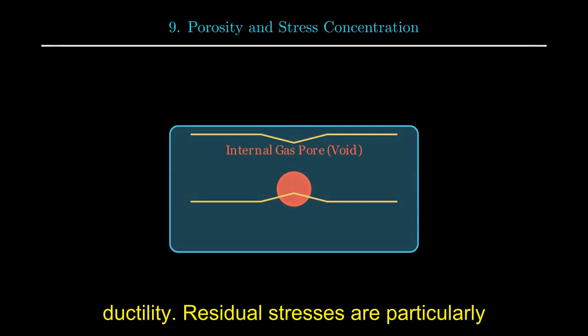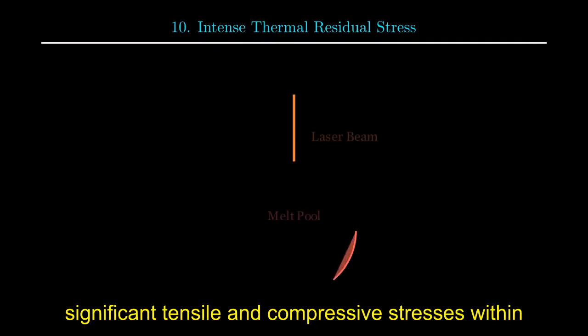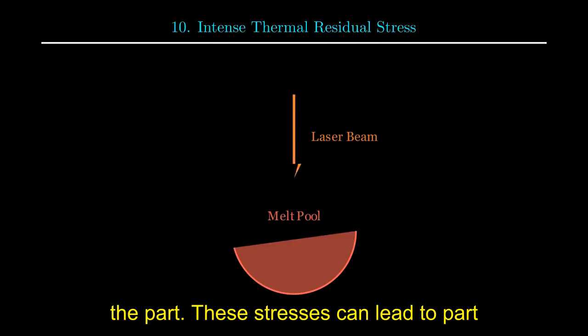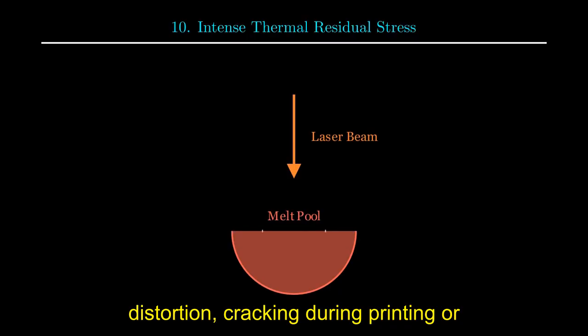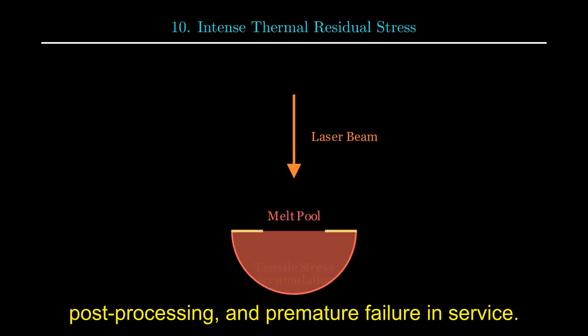Residual stresses are particularly pronounced in 3D printed metals due to the extreme thermal gradients experienced during processing. The localized melting and rapid solidification, combined with the constrained nature of the build, induce significant tensile and compressive stresses within the part. These stresses can lead to part distortion, cracking during printing or post-processing, and premature failure in service.